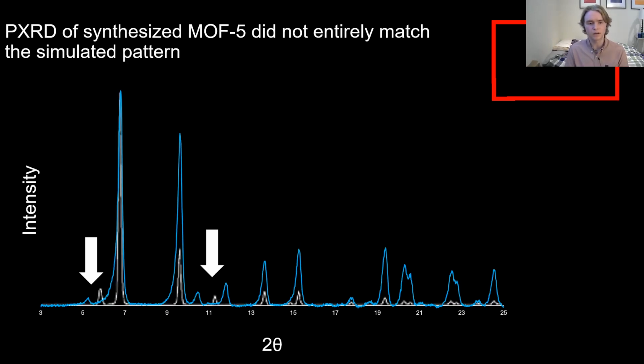So what we see here is that there are some discrepancies. For 1, there are 2 locations where my peaks don't match up with that of the simulated spectra, both at about the 5 and about the 11 2 theta mark. We're also going to see that my relative intensities aren't exactly right. I normalized the highest peak in both spectra to each other. That's the peak around 7 on the x-axis. We notice that the rest of the peaks in this simulated spectra don't really match up with the synthesized.